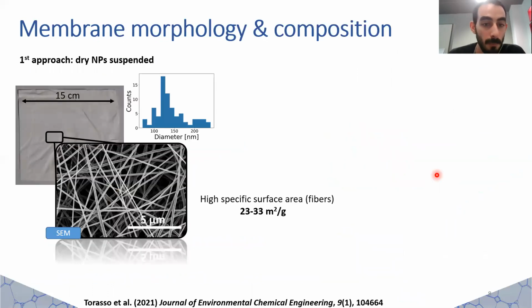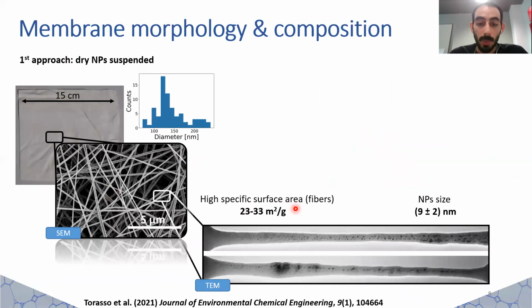So what did we obtain? A membrane like the one shown here. Some images reveal the nanofiber composition of the membrane with diameters ranging from 100 to 150 nanometers approximately. This membrane has an estimated specific surface area of 23 to 33 square meters per gram. Now, transmission electron microscopy revealed the nanoparticles lying inside the nanofibers. They are excellently dispersed and have a size of approximately 9 nanometers.